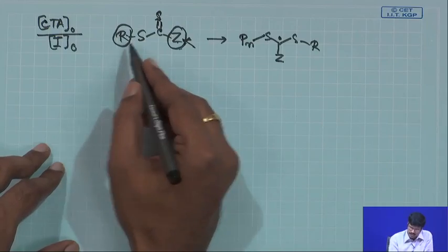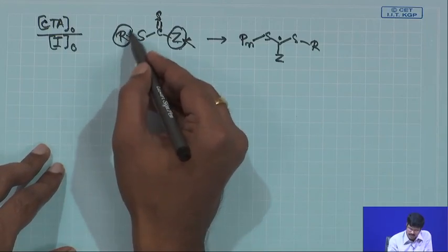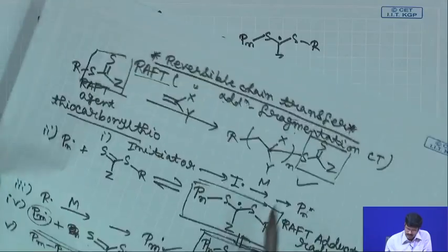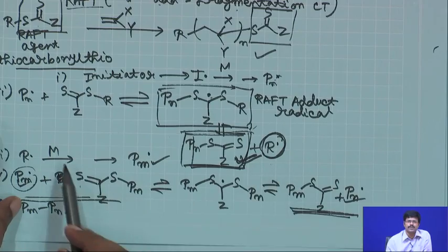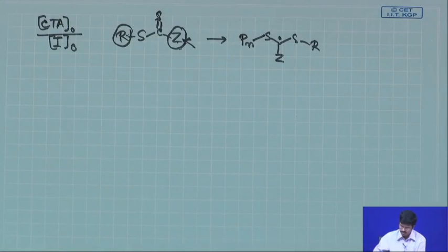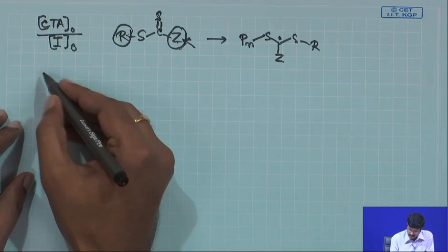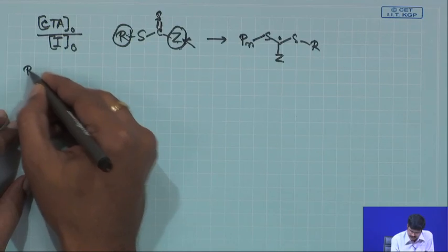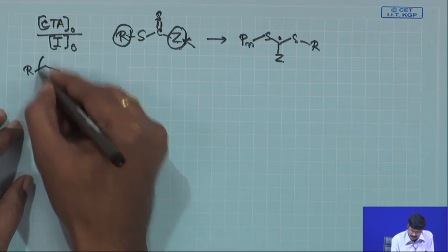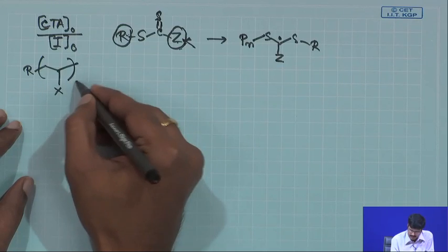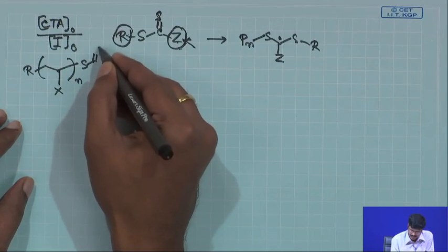so that it is a good homolytic cleaving group, because afterwards it will cleave off and act as the reinitiating species here. So, if you want to create, say, a diblock copolymer, what you can do is start with this macro initiator, because you first create this polymer with your chain transfer agent.